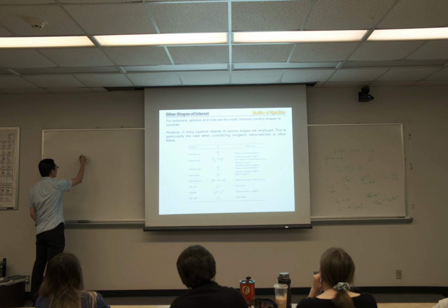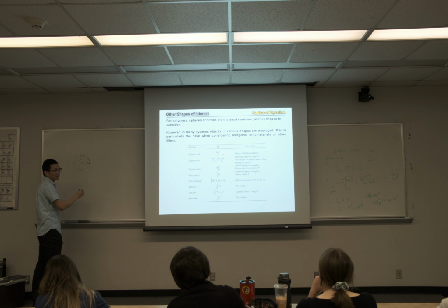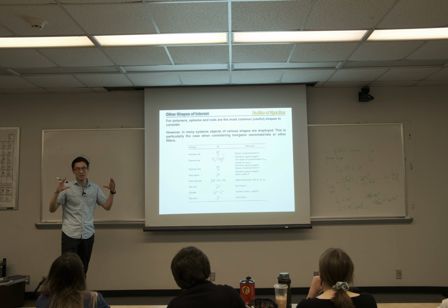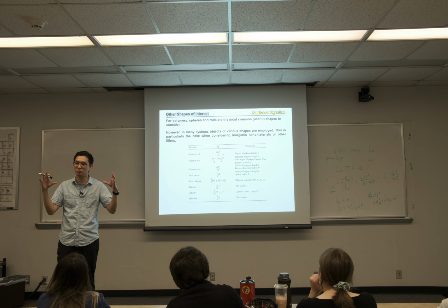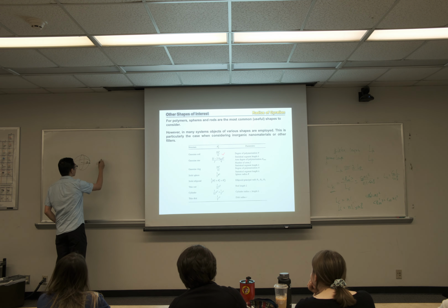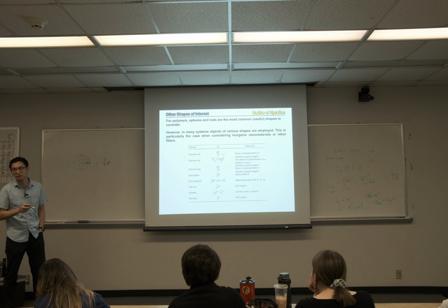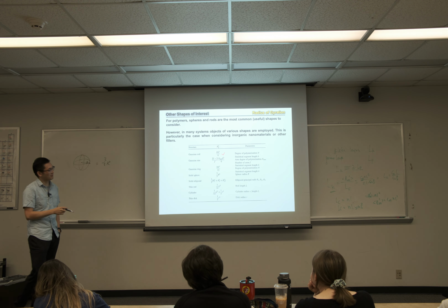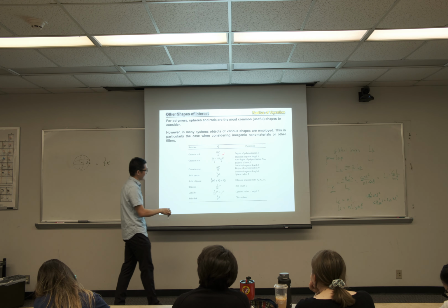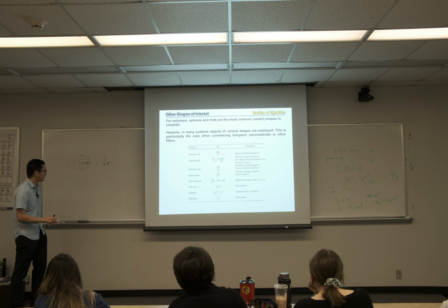But something that is easier to comprehend is a solid sphere. So if we have a sphere, I'm going to be terrible at drawing, with a radius of r. RG is actually not the radius of the whole sphere. When you calculate, RG squared is 3/5 of r squared. Okay? It can be homework for you guys. And let's take a look at thin rods, and we can work together on this in class.